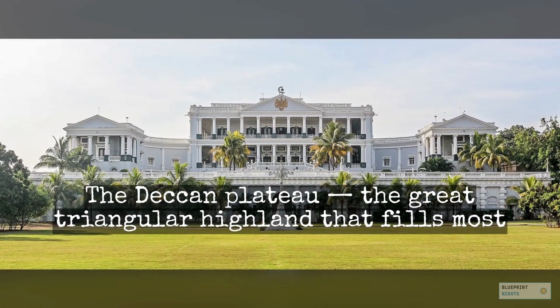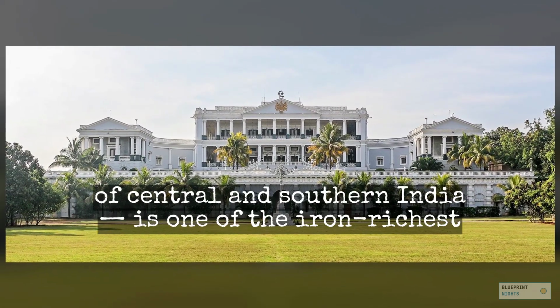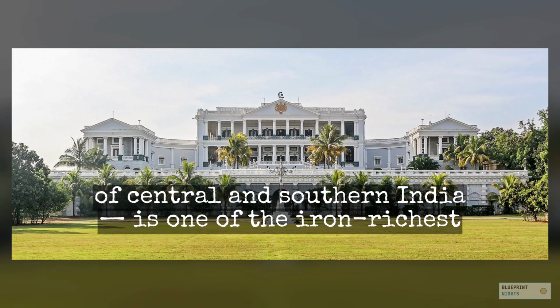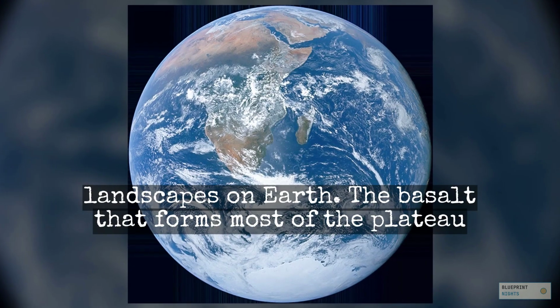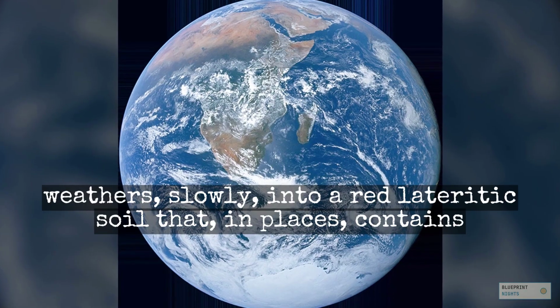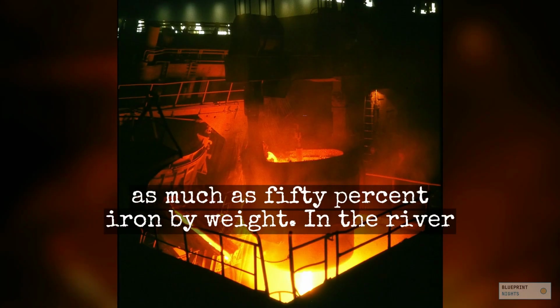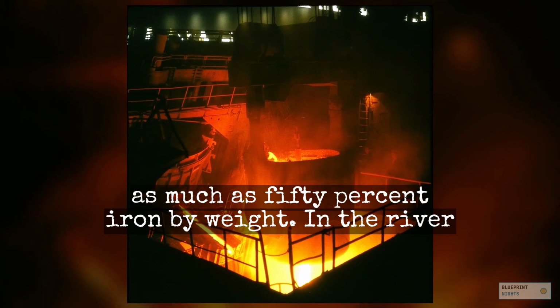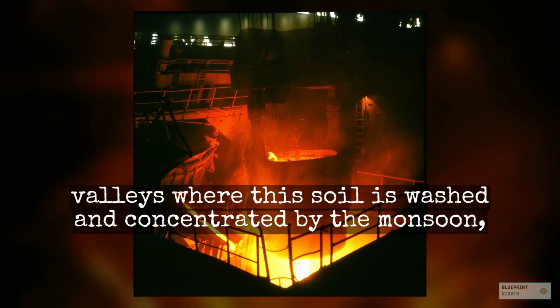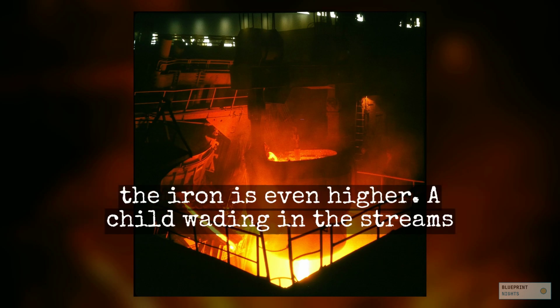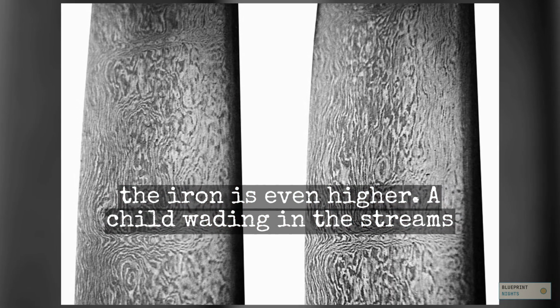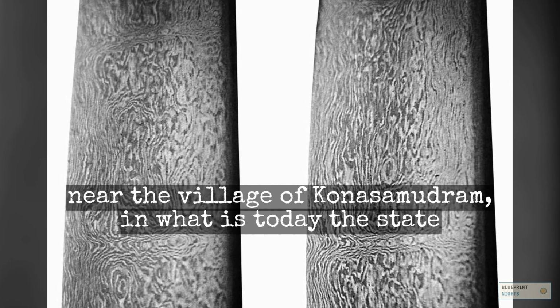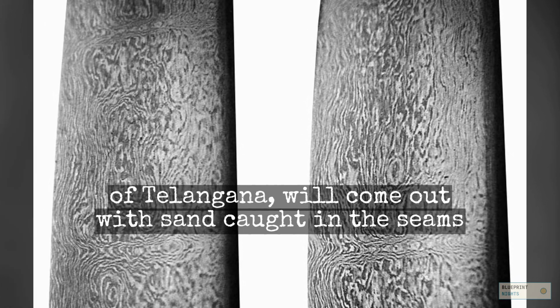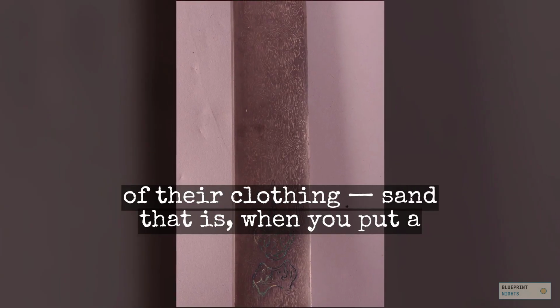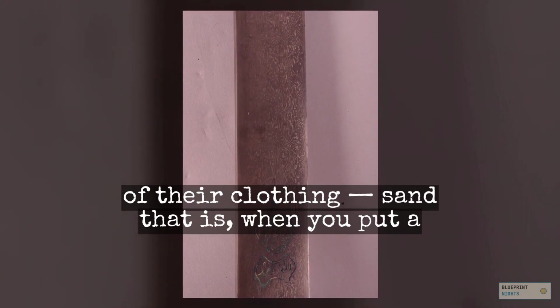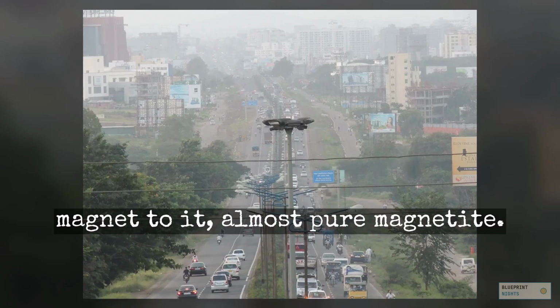The Deccan Plateau, the great triangular highland that fills most of central and southern India, is one of the iron-richest landscapes on Earth. The basalt that forms most of the plateau weathers slowly into a red lateritic soil that, in places, contains as much as 50% iron by weight. In the river valleys where this soil is washed and concentrated by the monsoon, the iron is even higher. A child wading in the streams near the village of Konasamudram, in what is today the state of Telangana, will come out with sand caught in the seams of their clothing. Sand, that is, when you put a magnet to it, almost pure magnetite.